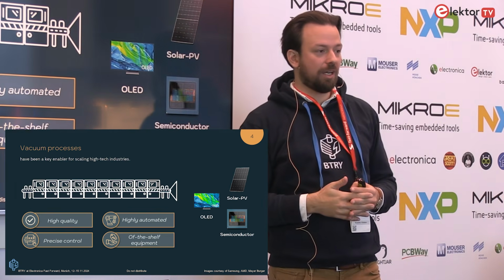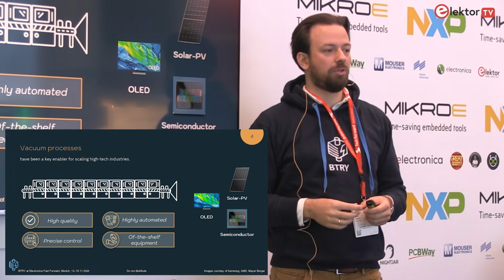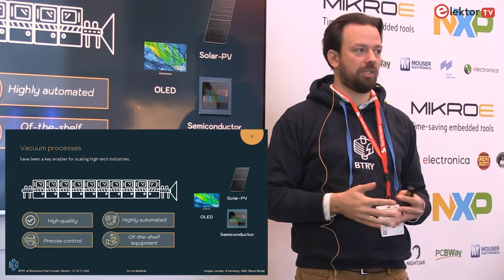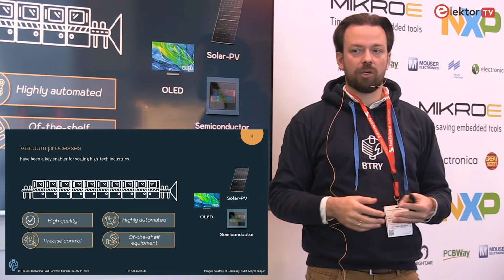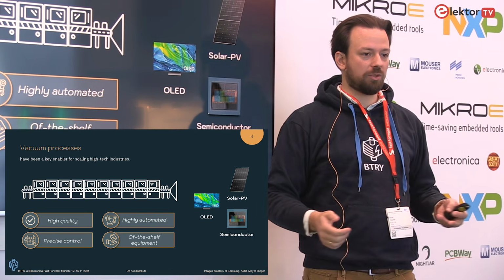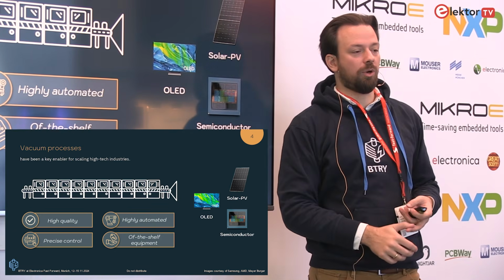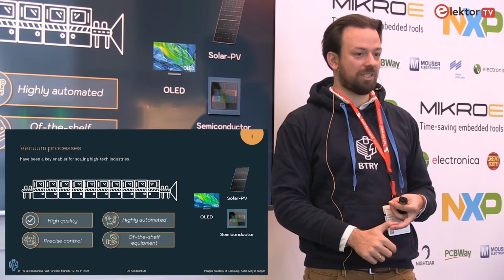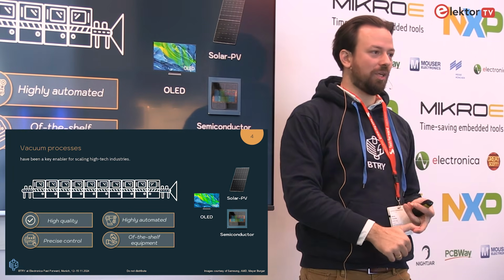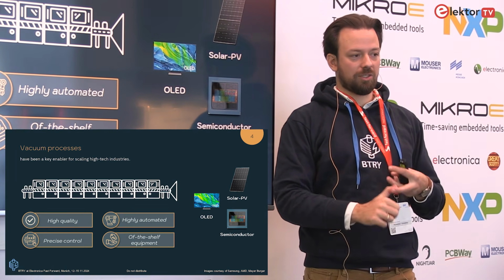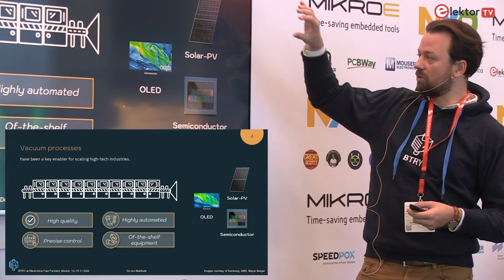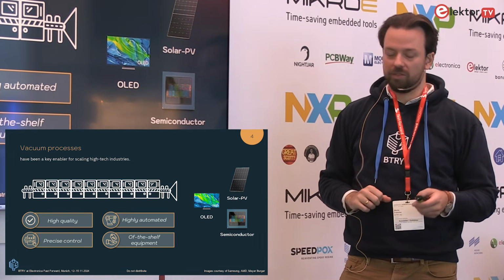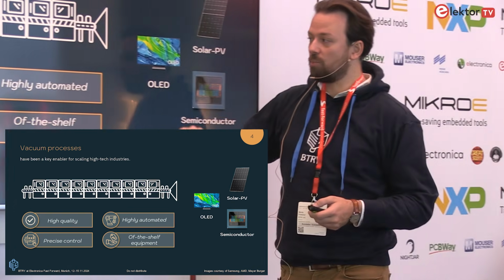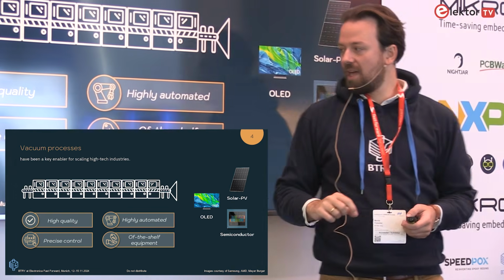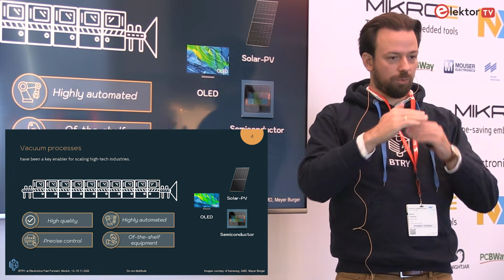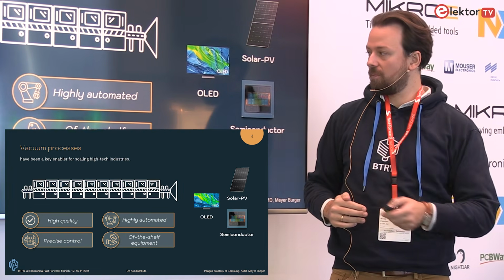There's one key difference. We use vacuum processing to build these batteries, where traditionally it's usually liquid processing. Vacuum processing has established processes in many industries, such as OLEDs, for example, where they worked for 10 years to replace vacuum processing with liquid processing. So far, not successfully. So this is still a very widely used technique. It is also used for solar and semiconductors. It is especially important if you need very high quality films with a precise control of the thickness, which we need, especially if we grow these on top of each other.